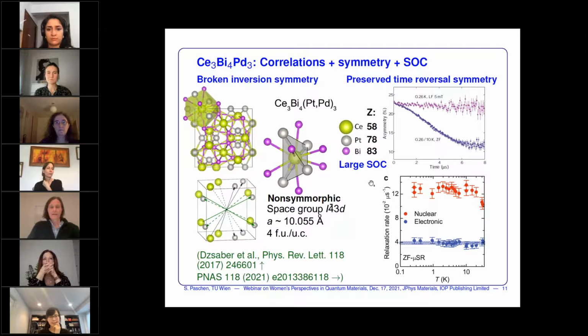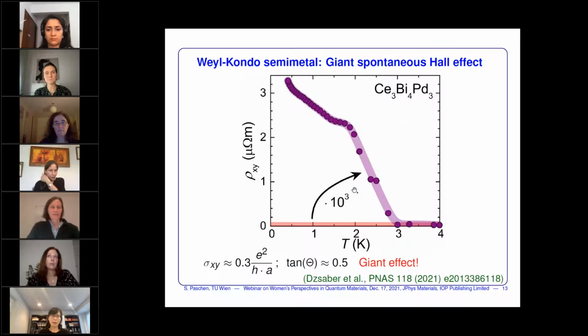So in this material that I'm showing here, cerium-3 bismuth palladium-3, we have all this. And indeed, we found a very interesting new topological, strongly correlated phase, which we dubbed Weyl Kondo semi-metal. So let me just highlight one of the exciting properties of this material. And that's shown here. It has what we call a giant spontaneous Hall effect.